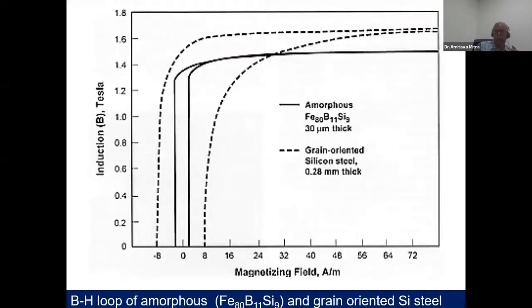And you can visualize this advantage. The dotted curve is basically the iron-silicon crystalline alloy, which is called silicon steel, and the solid curve is basically the iron-boron-silicon alloy. And you can see there is a disadvantage because we are not reaching saturation induction of more than 1.6 Tesla.